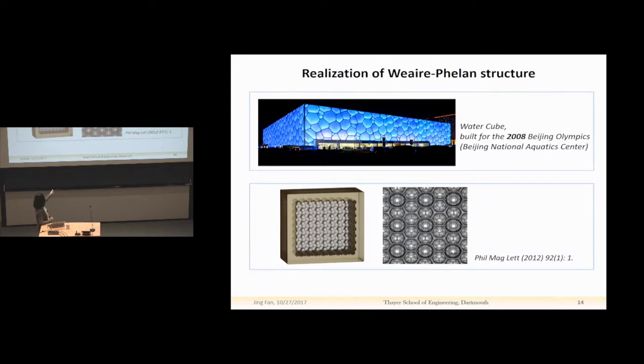The whole system has about 1,500 bubbles, and each bubble has a diameter of about 2 millimeters. So they are kind of big. And we thought that since the Weaire-Phelan structure has a pretty low energy compared to even the Kelvin structure, if we can observe the Kelvin structure in the experiment, in principle we should be able to get this if we give a little bit of guidance to the droplets, right?